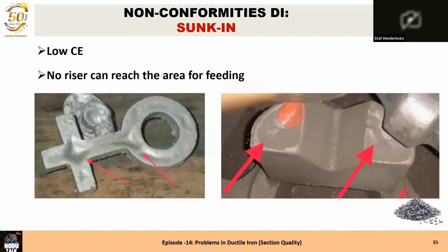Here are some castings, and there you see very well the problem of this sunk in. On the right side, you can also see it's a kind of bearing cap, in the center of the feet you lack material, and many times when the customer starts machining, he cannot get a completely machined surface there anymore, and then he will not accept the casting. It has to do with low carbon equivalent. Why has it to do with low carbon equivalent?